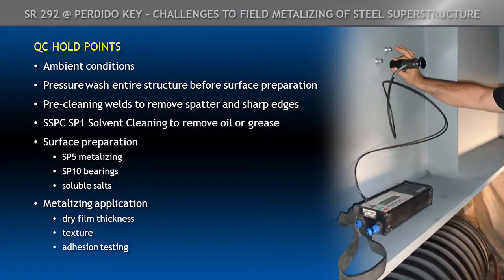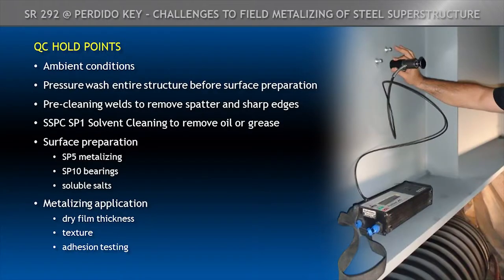We also did SSPC SP1 solvent cleaning, and then the surface preparation, as I said before, was SP5 for the metalizing. And then for the bearings, we went back to the typical FDOT spec that we use, SP10 near white blast cleaning, and we check for soluble salts after final surface preparation. And one of the things, because of our environment in Florida, that they've written into the spec too that contractors bid, is checking for soluble salts in between coats. Some reasons for that, just because of the area we're in. For the metalizing application, we checked dry film thickness and required 8 to 12 mils.